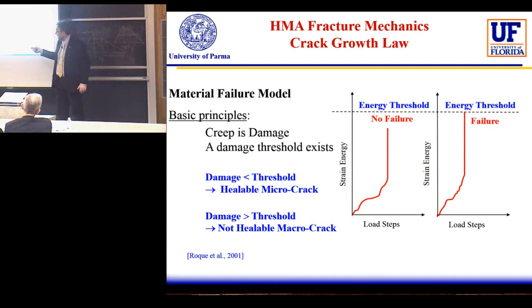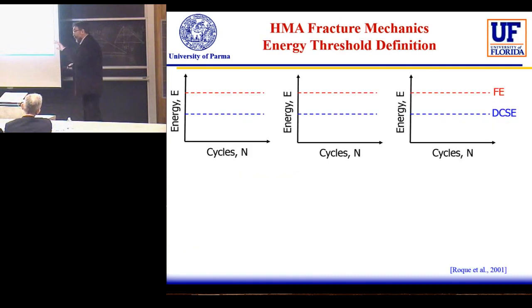We can see not visible and visible from another point of view. Following this approach, we can define two different thresholds: one named dissipated creep strain energy and one that is the total fracture energy. Dissipated creep strain energy is the energy dissipated by the creep of the material. So you apply load, the material starts to dissipate energy, and if the micro cracks coalesce and grow, you have the first crack that appears in the material.